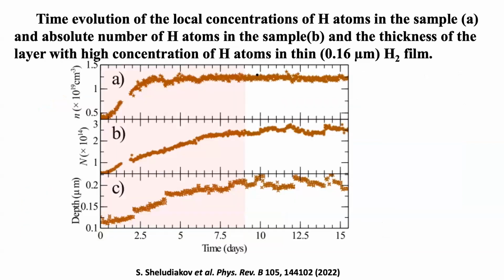So after that, we decided to prove that we are right, and we understand that we can create the sample cell, thin sample cell, and if we have really this diffusion rate after some period of time, like 9 days, this high concentrated layer should come to the flat mirror and should recombine. So the concentration after some period should not change.